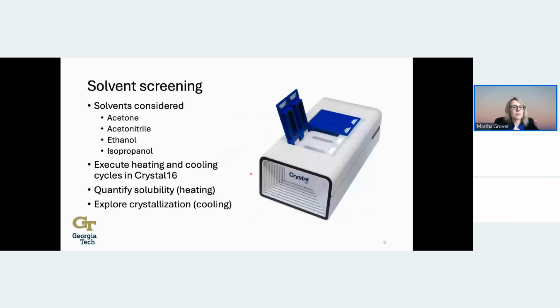Having established that we did have the monohydrate and that the water could be lost under a variety of conditions of temperature and humidity, we decided to do some solvent screening in our Crystal16. We considered 4 different non-aqueous solvents: acetone, acetonitrile, ethanol, and isopropanol. We executed heating and cooling cycles in the Crystal16. We used the heating cycles to quantify the solubility of our crystalline form, and then cooling to explore crystallization.